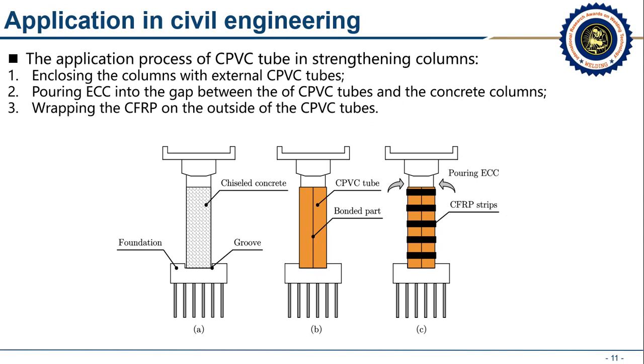CPVC tubes are split vertically into 2 parts and glued around the columns as permanent protective shells, improving durability and ductility. In addition, CFRP strips as circumferential confinement to increase strength were wrapped around the CPVC tubes at a certain spacing, and the ECC is poured into the CPVC half tubes. The CPVC tubes act as a cladding layer to enhance the impact resistance. Detailed operation procedures are shown in Fig 1. This hybrid strengthening system that is expected to take all advantages of those materials is now first proposed in the literature for repairing existing concrete columns in terms of strength, ductility, durability, and impact resistance.